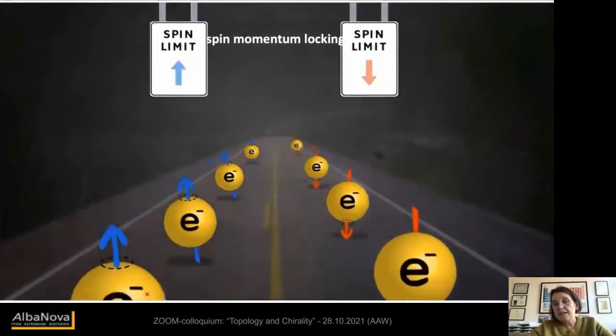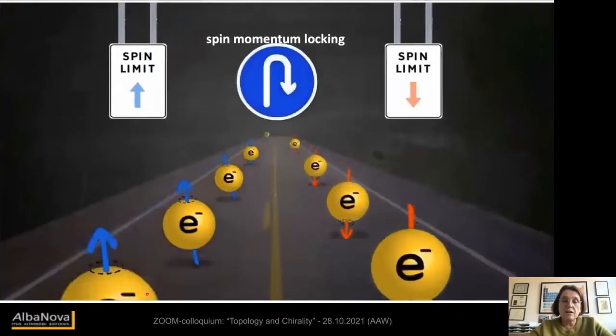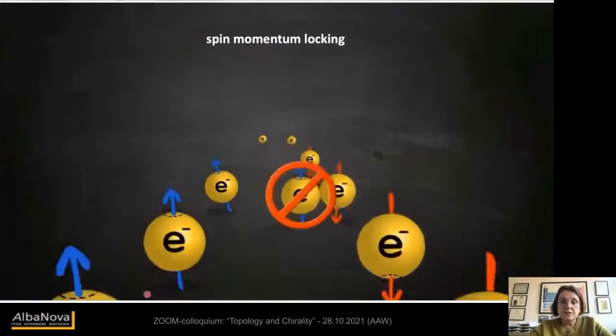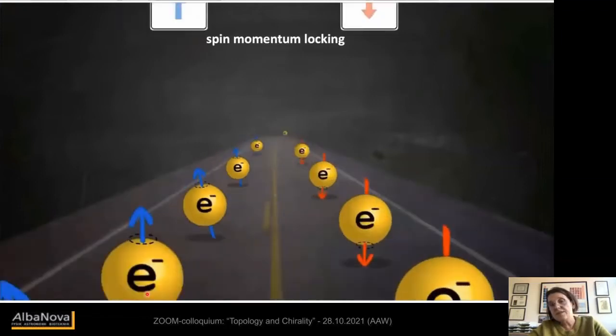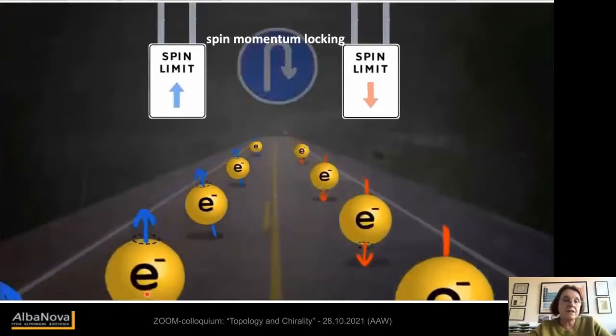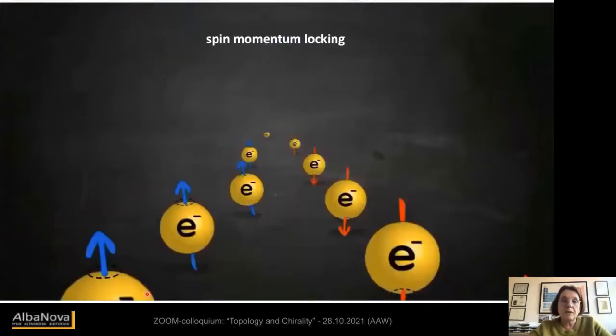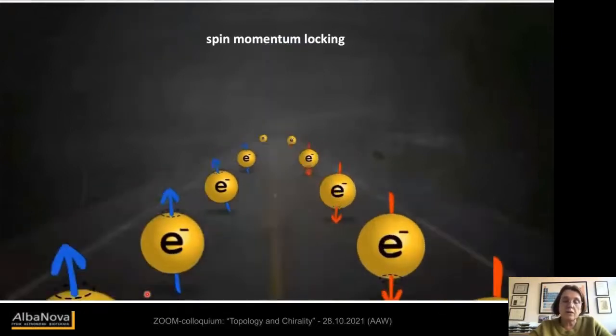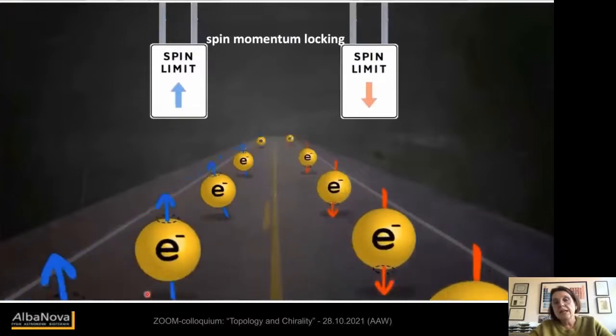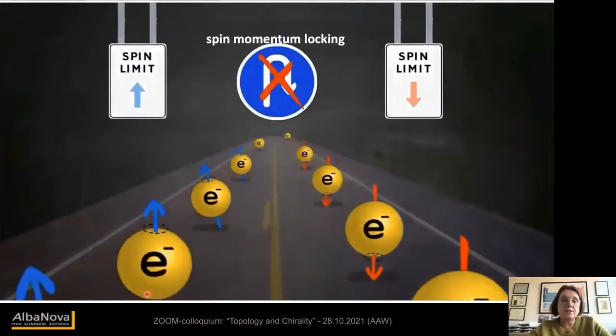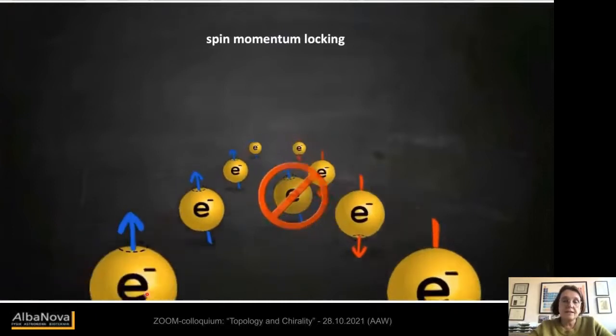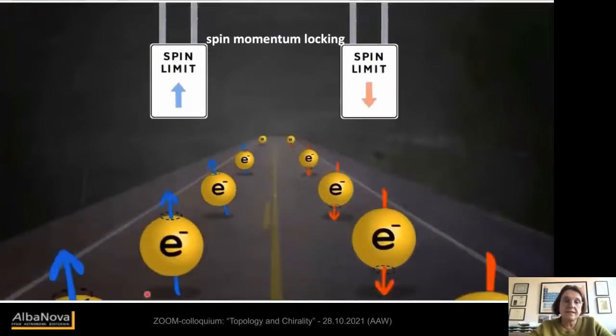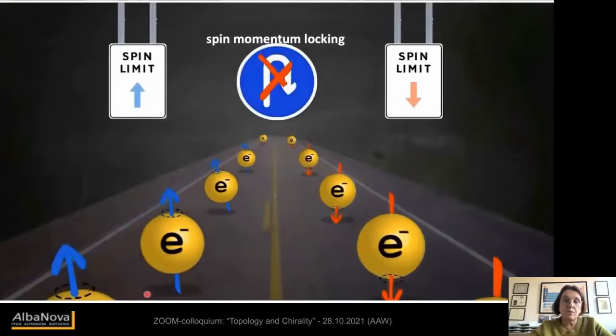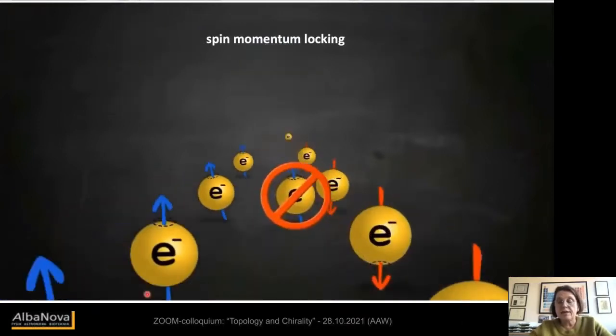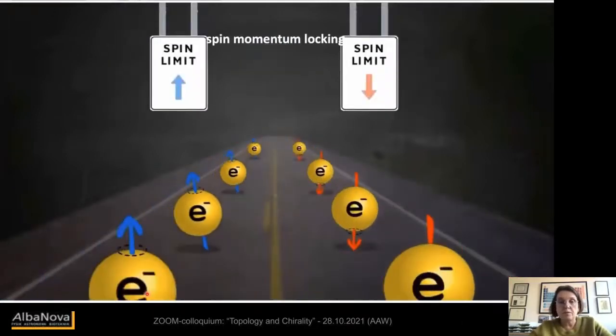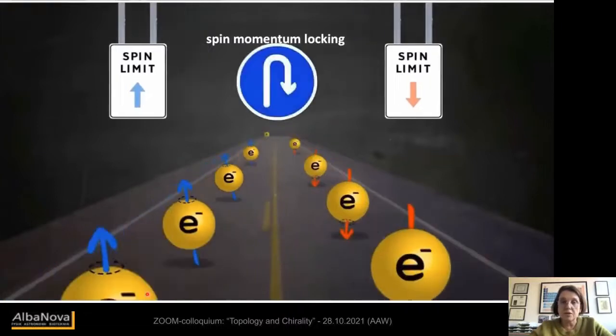So this also leads to the observation that if the spin and the momentum are locked, the electrons cannot be scattered. So they behave like on a highway. They are not allowed to scatter into the other spin direction. And this leads to very interesting observations. I don't have the time to talk about this. Many of these compounds, the topological materials, show very high mobility. The electrons flow more like a fluid than like a gas. We see that the scatter rates are suppressed. And we might see even spin polarized currents, as was observed recently in some topological chiral crystals.